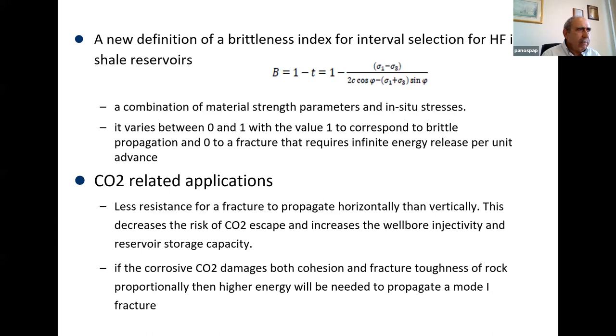The second question is by Makhti Haddad. Consider that the common fracture toughness measurement for reservoir rocks using the scratch test gives values of 1.7 megapascals square root meter. Will you please explain the conditions to obtain 35 megapascals, 20 times more? And this is what we calculated.